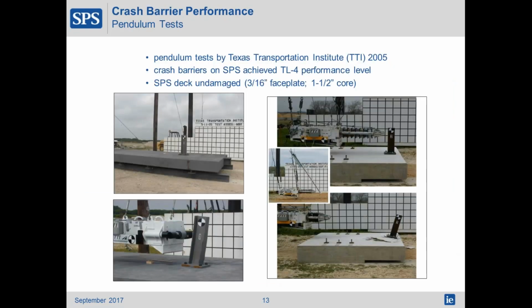This picture is a side-by-side comparison of an SPS deck and a concrete deck, where pendulum tests were conducted by the Texas Transportation Institute back in 2005 to evaluate the performance of SPS decks. What I'm going to show now is a video of a pendulum test that was conducted. In this case, the SPS deck remained undamaged, and it should be noted that the thickness was less than 2 inches. What you see in front here is a fascia plate. Compare this with concrete, where we can see rupturing of the concrete deck surface.